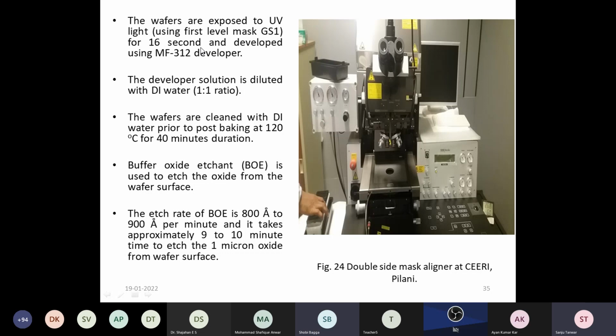Now, in positive photoresist, the part where the light goes becomes soft, and the remaining part stays hard. Then it is developed using the developer solution diluted in DI water. Then the wafers are cleaned with DI water prior to post baking. Post baking means after exposure you heat it at 120 degree for 40 minutes.